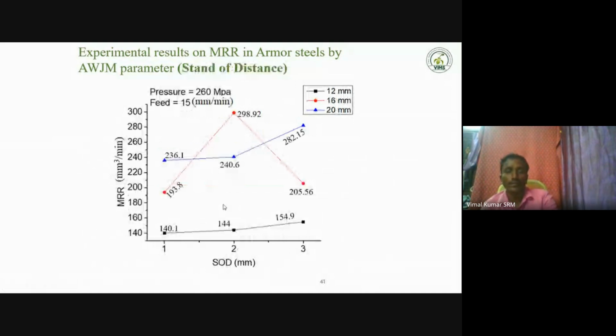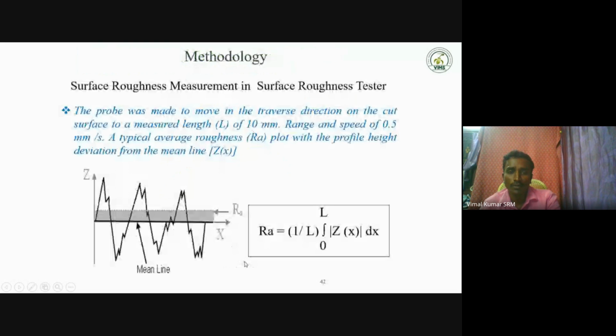So here standoff distance influences the material removal rate. Yes, definitely, because as we increase the SOD, a higher material removal rate occurs. This graph is the best example. For the 12, 16, and 20 mm plates, we do not get straight lines; we get uneven values. So in this condition, SOD influences the material removal rate.